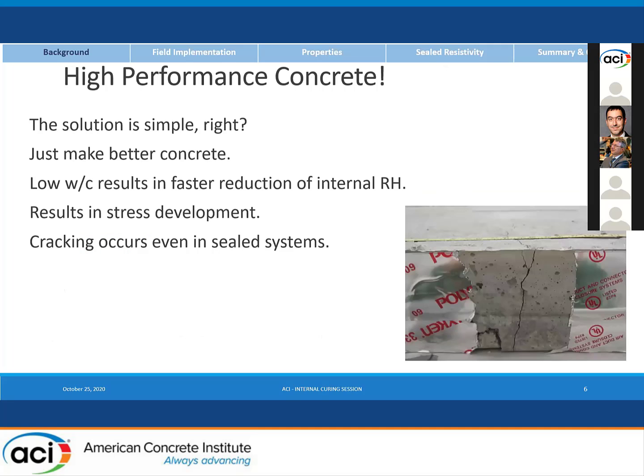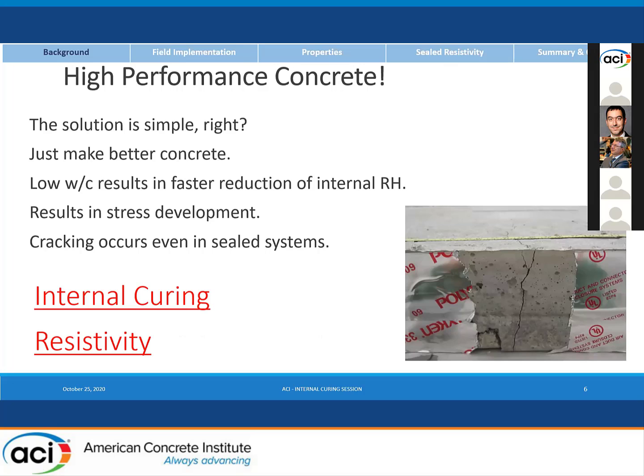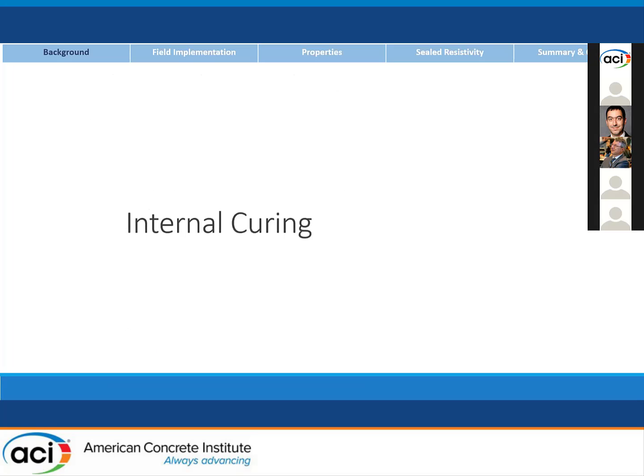And so it really does go back to, well, this should be simple, right? We should just be able to make better concrete. But we did indeed try that back in the 90s with the high performance concrete experiments. And we found that we had extraordinary early age shrinkage cracking problems. And it turns out that it's driven by the reaction of the concrete itself. And so you get internal self-desiccation. And so that's where the internal curing is going to come in. And then we'll go ahead and we'll talk about the resistivity method as how I would recommend that we are actually implementing a specification to be able to ensure that we're getting that service life.